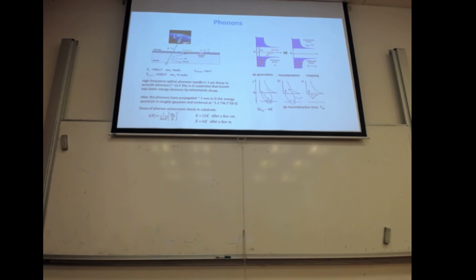And then let's see how the phonon, because of this anharmonic decay in the substrate, goes down in energy over time. Basically you see that it goes like this, scaling, and this is what it means: a phonon, after a few centimeters, has an energy of around 12 Kelvin. So 12 Kelvin, you see, is more than enough to break the Cooper pair of the aluminium. And after meters, because of this anharmonic decay, it is at the level of 4 K, so it still can break. So there is no way.